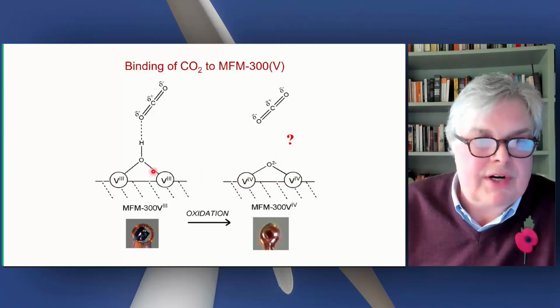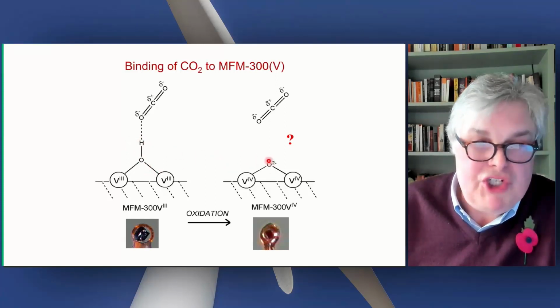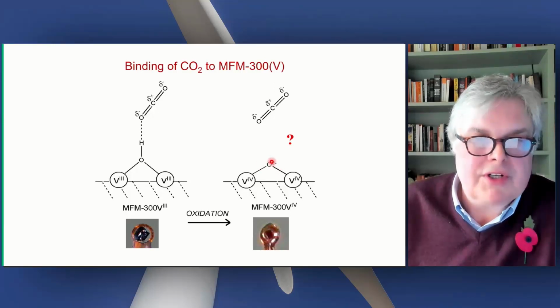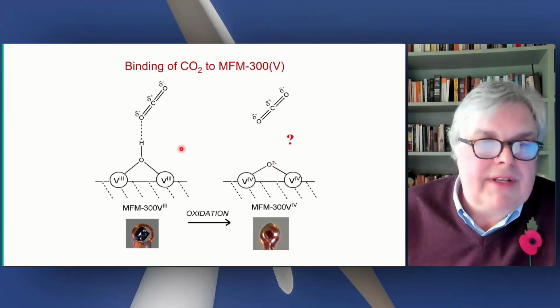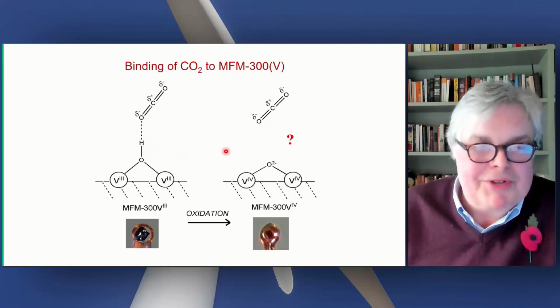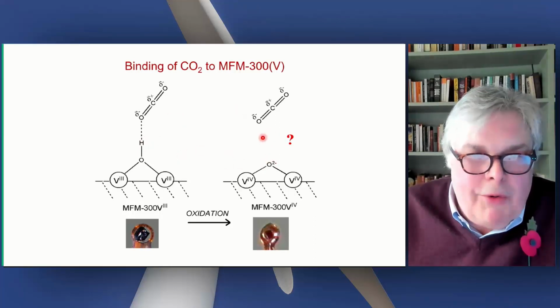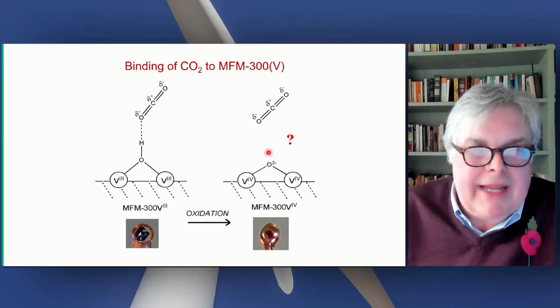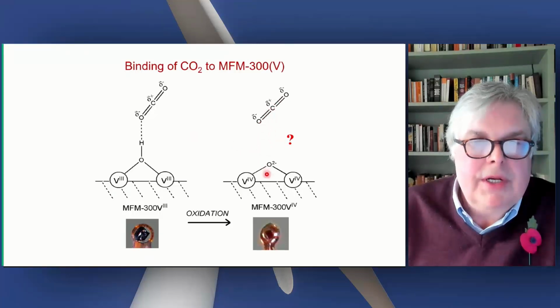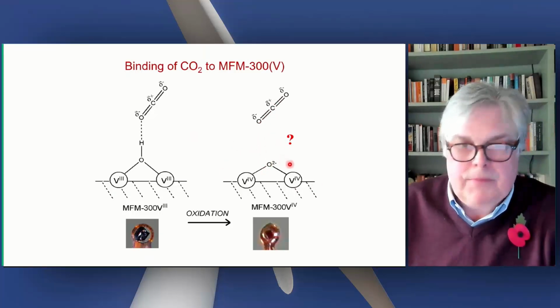These two are isostructural, but what happens is you lose the proton and the hydroxide is oxidized, or sorry, is reduced to an oxo group here. It's not an oxidation, it's a deprotonation. So now you've lost the hydrogen bond capability to the CO2. So what happens in this material?